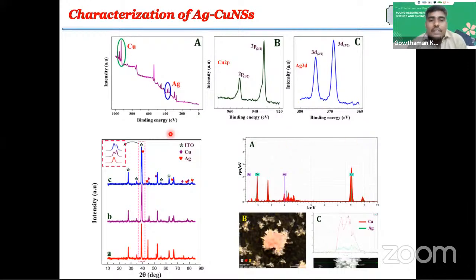Okay, thank you. The formed bimetallic nanostructures can be characterized by XPS and XRD. In the XPS, there is a formation of Ag 3d band and Cu 2p band, confirming the formation of both copper and silver in the metallic state. That is important, because we take metal ions, that is Ag plus ion, but here what is obtained is silver nanoparticles. So this is important. And the formation of AgCu is confirmed by the Ag core and copper shell.